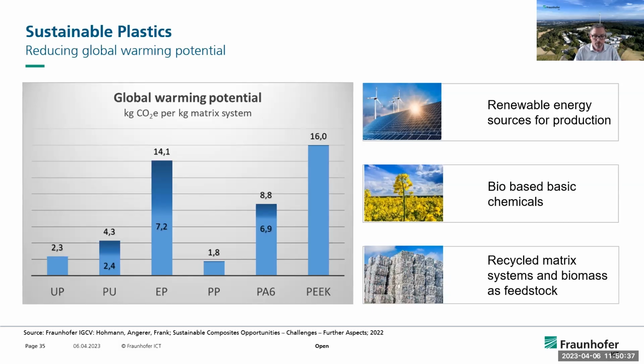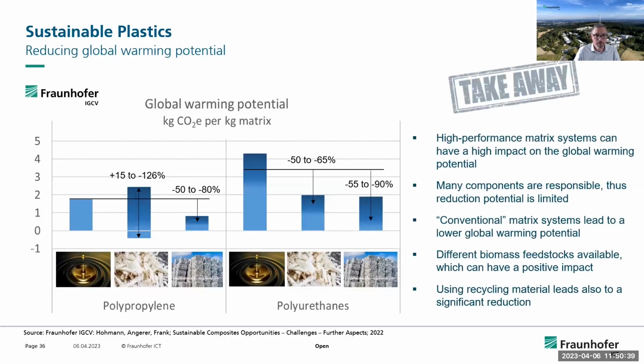And just to look into two materials, we had a closer look at polypropylene and polyurethane, since they are quite established and often used, especially in the commodity field. It's heavily depending on the feedstock. Polypropylene you can derive from a natural source like wheat or sugarcane, and it's completely different in terms of their global warming potential. However, when we use recycled PP, we can significantly save up to 80% global warming potential,